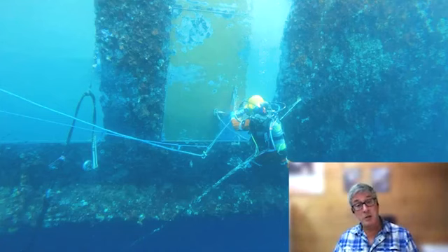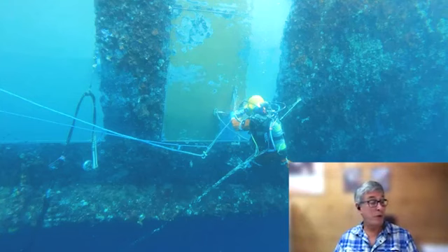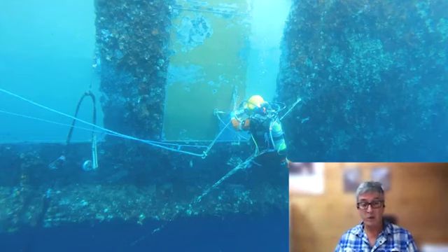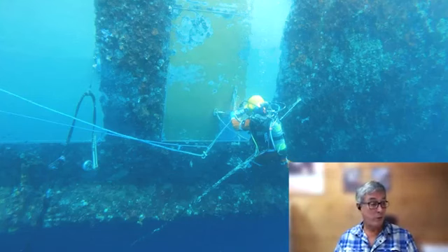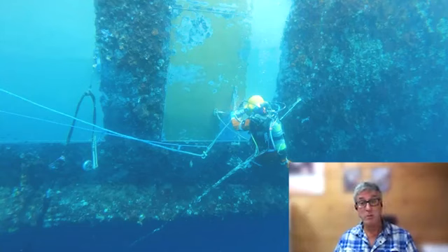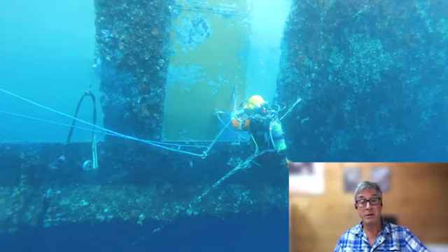We always put a second coat on simply because it fills the troughs left behind. It's not a dead flat surface when we finish painting. And if it fills the troughs, then you're guaranteed to be well over 300 to 400 microns when you've completed the work, and that means all the thin areas the guy might leave. Nobody's perfect.